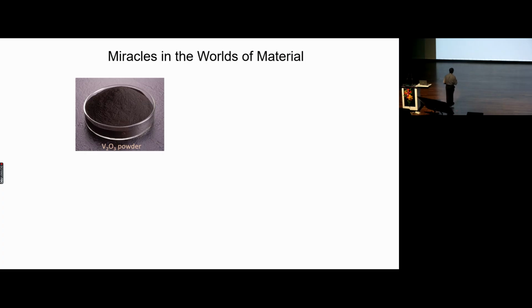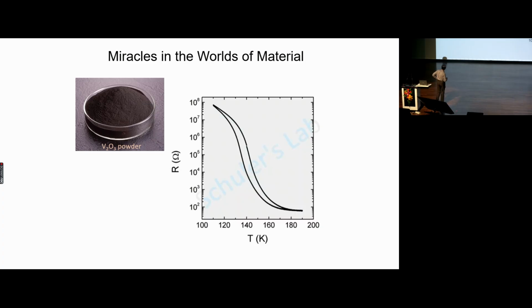Here is a material which is powder and evidently not malleable. Malleable material cannot be made into powder, and it's an oxide, V2O3. The question is, is it a metal or not a metal? By all signs of it, looking at it, one would say it's not a metal, simply because it has no quality of the metal. In fact, if you measure its resistivity, asking the question of its conductivity, you'll find that it's highly insulating. Here is the plot of resistivity. At a low temperature, it has this fantastically high resistance, 10 to the power 8 ohms.